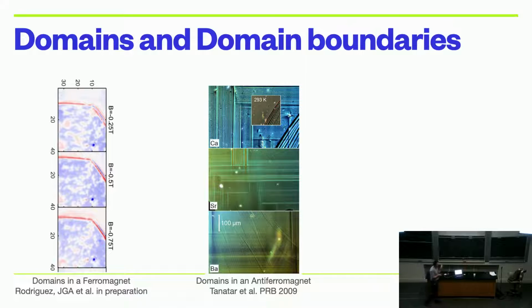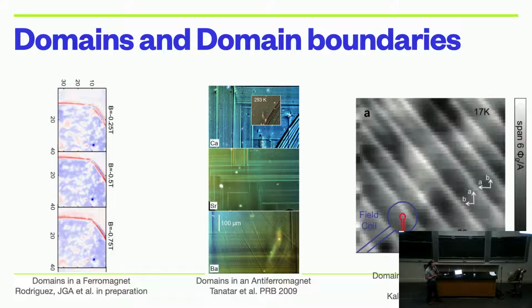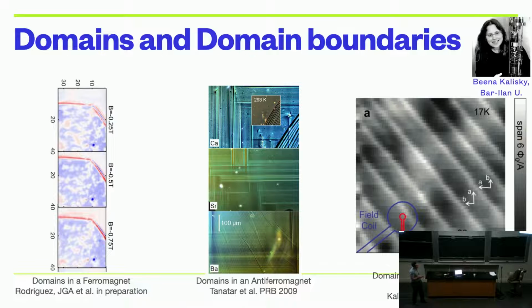Okay. So this led to one other thing, which is a result I had in my postdoc in collaboration with the Kathryn Moler group that has really kind of haunted me since. This is about 11 years ago. Here you're looking at domain walls of an iron-based superconductor, one of these materials. It was Beena Kalisky, who was a postdoc with me at the time. What she measured was, they have a scanning technique called the scanning SQUID, where they can measure the superfluid density, or measure where the system is superconducting in different parts of the sample.